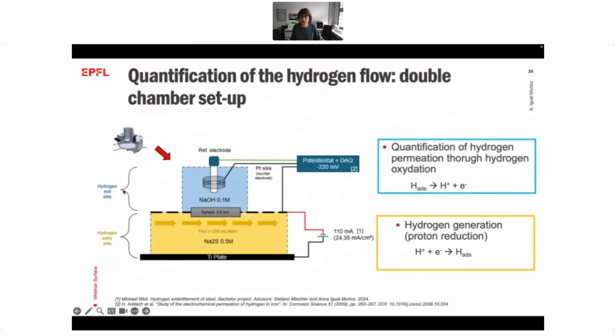So we developed, together with ERTEC, an electrochemical permeation cell, based on the classical permeation technique that was introduced by Devanathan and Stachurski. This is known in electrochemistry, where we have a thin membrane, in this case our steel sample of 3.5 millimeters in diameter, and then we charge under the same conditions we observed in the previous example. We charge the steel in the entry chamber, and hydrogen diffuses through the sample, where in the exit chamber it can be quantified, or oxidized. So in the generation chamber, we reduce the proton. In the exit chamber, we can oxidize the proton, so we quantify the hydrogen flow.